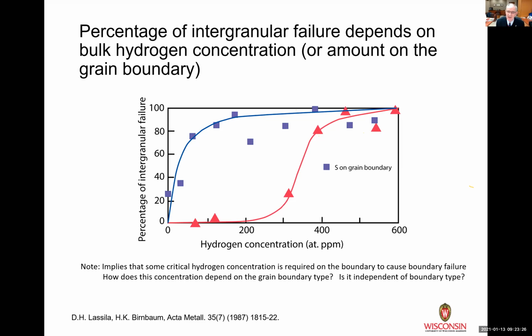He also showed one of the other complicating things about hydrogen embrittlement as we try and understand it, and understand its effect on the grain boundary. If you actually add sulfur to the grain boundary, along with the hydrogen, the two act synergistically, and you only need a little bit of sulfur on the boundary, a little bit of hydrogen, and you'll get much more intergranular failure than you do if you have a pure boundary. So as you think about hydrogen embrittlement mechanisms and how you could possibly get a transition from transgranular to intergranular, you also have to take into account this impurity effect.